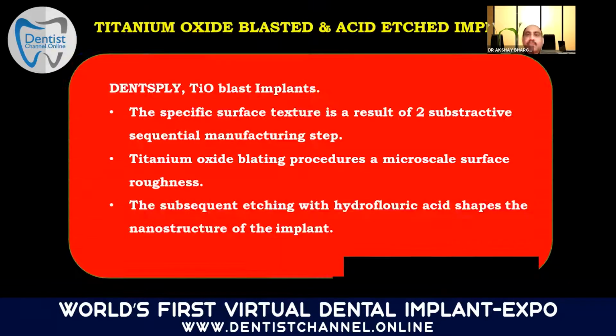Titanium oxide blasted and acid etched implants, DENTSPLY, TiO blast implants. This is another way of getting a surface treatment. So it's on a micro scale. You have two subtractive sequential manufacturing steps, with etching done with hydrofluoric acid.